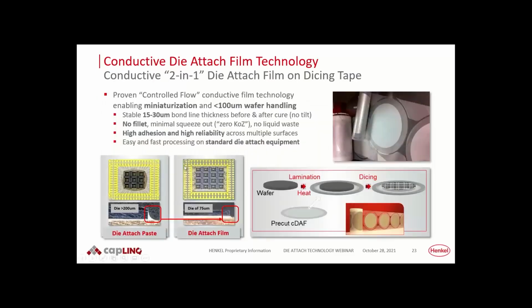And why should you solve these issues? Basically, especially when the parts are getting smaller, dies are getting smaller, you get multi-die packages, dies close to each other, then there is no room for fillet. So basically with a conductive film in this case, or a non-conductive film, you can make fillet-free, very, very small assemblies. So that's what we call also zero keep out zone. So very small, you can design dies very close to each other. And basically this was important for smartphones, especially consumer electronics, where more computing power and more ICs are getting into the same space.